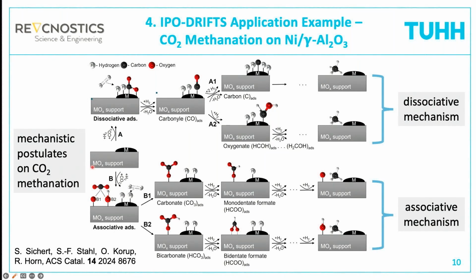And then there is another school of thought where people believe that the CO2 adsorbs on the metal oxide support, in this case gamma alumina, which is an amphoteric support. So we have oxygen sites and we have hydroxyl sites, and now the CO2 can adsorb on these basic sites, and we then get carbonate and bicarbonate. And then it is believed that the carbonate is reduced by hydrogen spillover to formate, either monodentate formate or bidentate formate, and then we get further reduction down to methane.